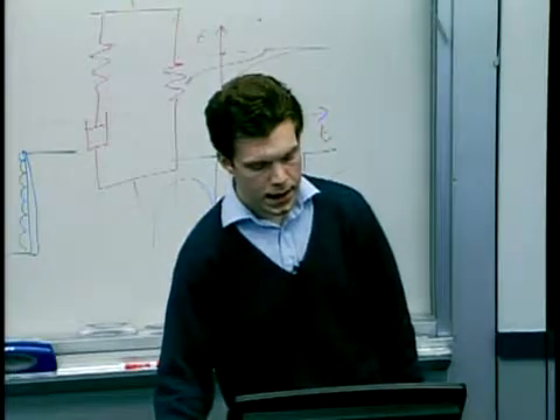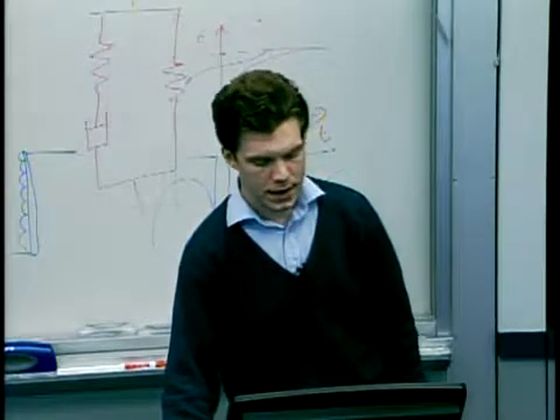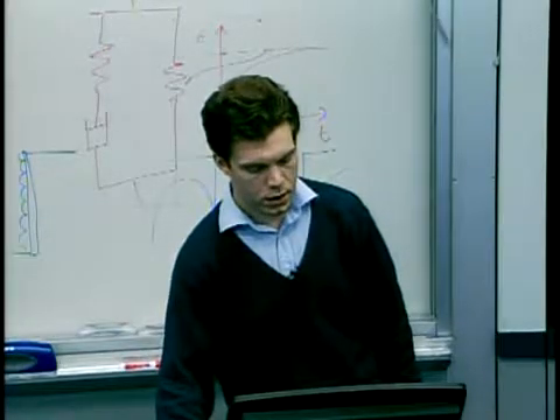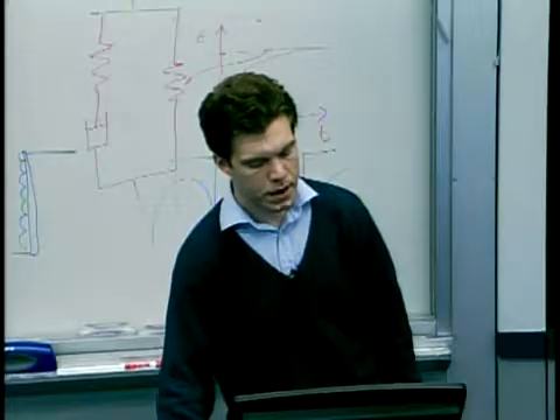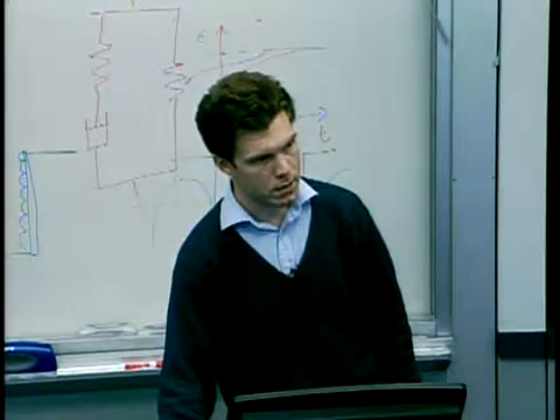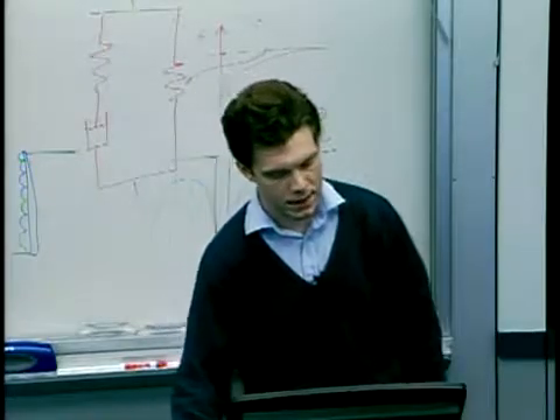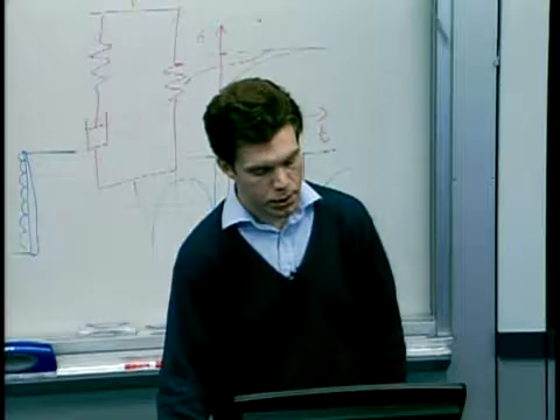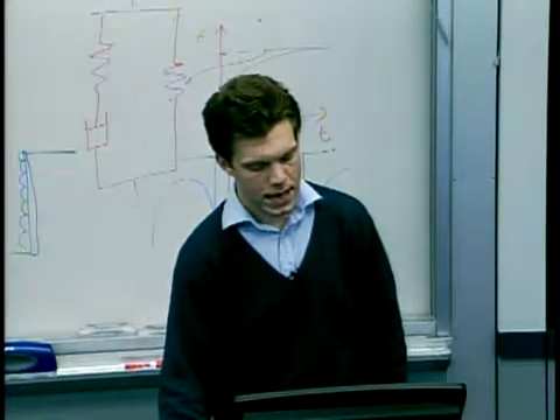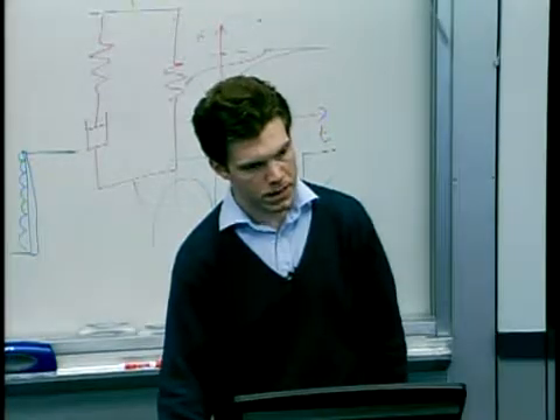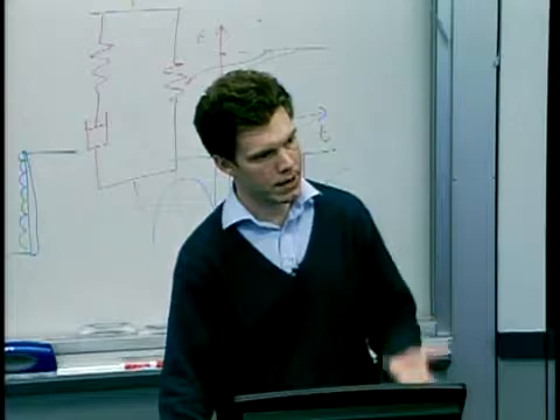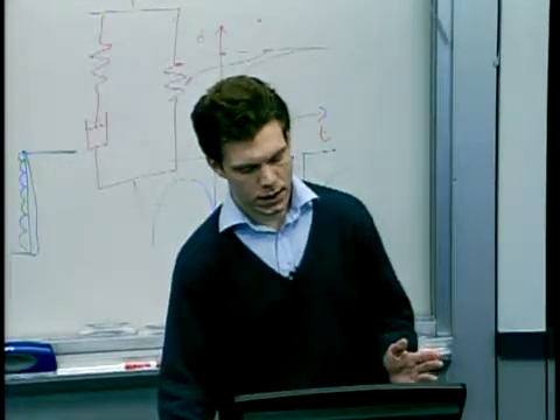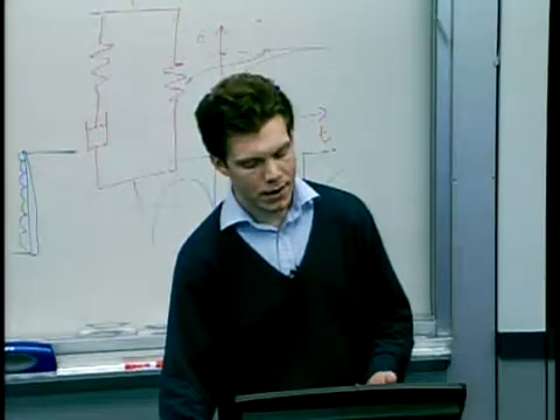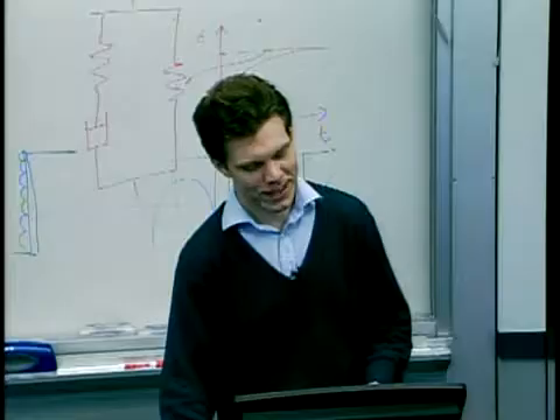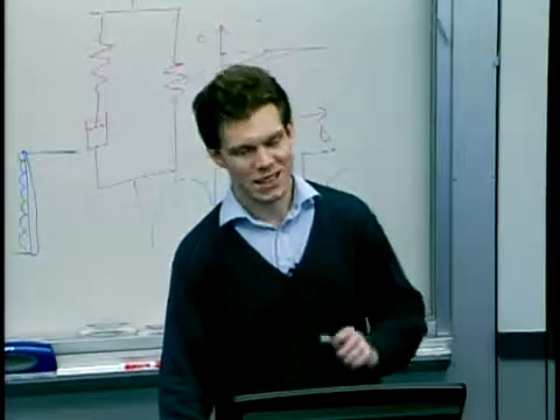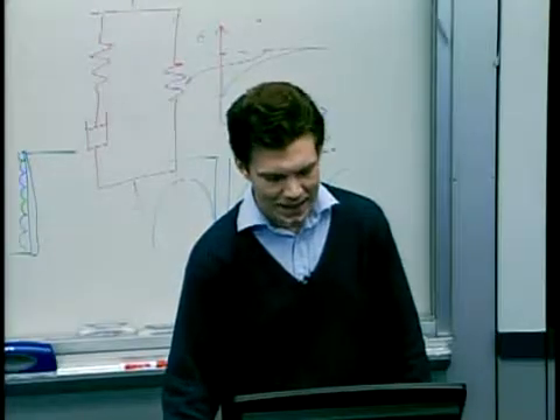If you demold at 50 degrees C, so well below glass transition, and then pull the stamp off, this is a cross section through the part, then you get this horrendous ridge on the side of the feature nearer the edge of the part. If you demold, say, well above glass transition at 120, you get this blue line. So you get some bowing of the base of the feature where material has sprung back, and you get splaying of the sidewalls, and this was repeatable over many samples. However, if we can hit 110 degrees C on the nose, we get a nice flat feature, we get nice flat sidewalls, and we get no ridge at all, and that would be great. But again, that's the thing.